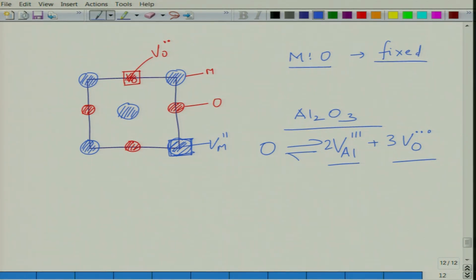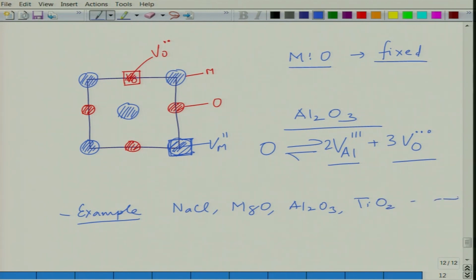So this is called a stoichiometric defect. It doesn't change the stoichiometry of the system. And the materials which show this kind of defects are things like sodium chloride, magnesium oxide, Al2O3, TiO2. Many of these materials show this kind of Schottky defects. Second defect in this series is called Frenkel disorder.